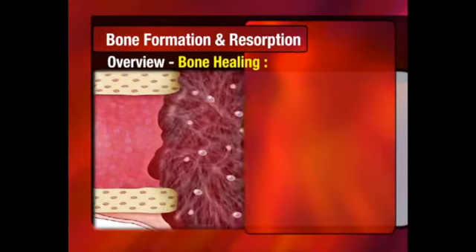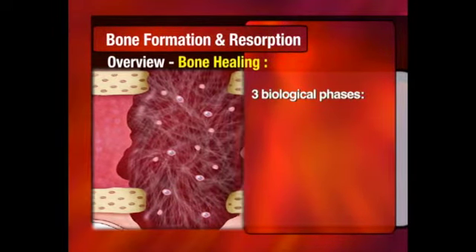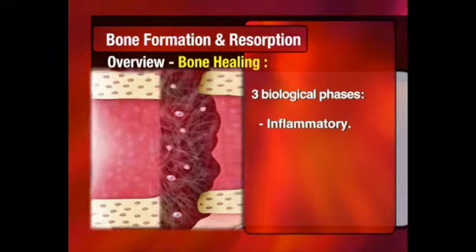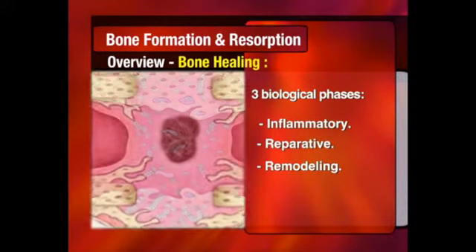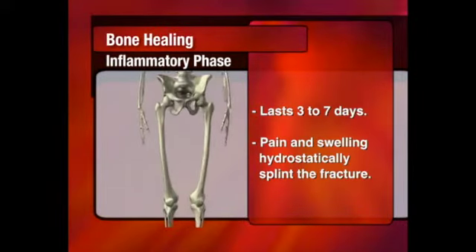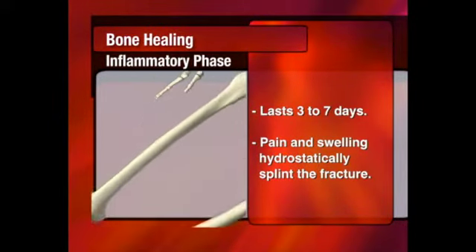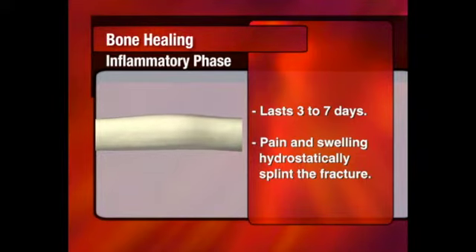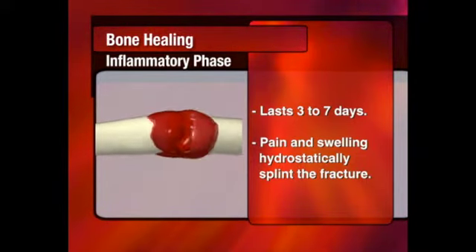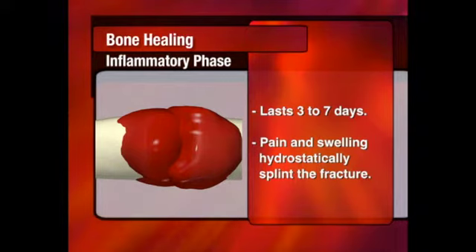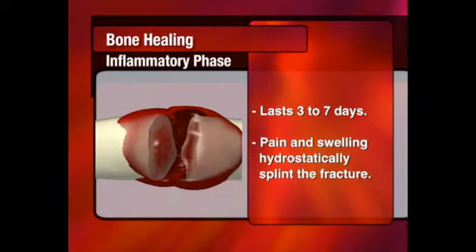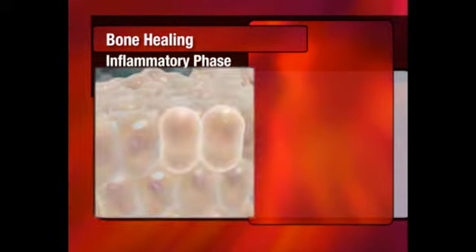Fracture healing may be divided into 3 biological phases: the inflammatory phase, the reparative phase, and the remodeling phase. During the inflammatory phase, lasting 3 to 7 days, pain and swelling effectively act to hydrostatically splint the fracture. A hematoma forms. Inflammatory cells infiltrate the site, and there is vasodilation and serum exudation. Chemical mediators recruit stem cells to transform into cells that mediate bone formation.